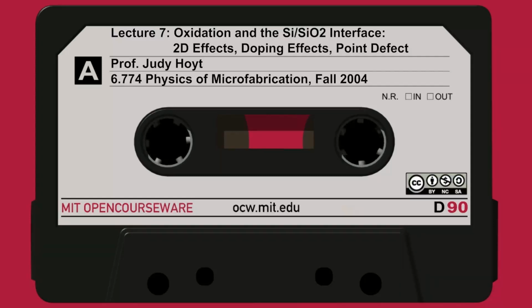Okay, so let's go on to slide 10. There's one more parameter that we need, because we said the oxide is a glass and it's flowing. The glass flows differently, or its ability to flow depends on temperature. And that is expressed through a viscosity parameter, eta. And in fact, the stresses in the oxide are high enough that the viscosity itself, its rate of flow, actually is a function of the stress in order to model it accurately.